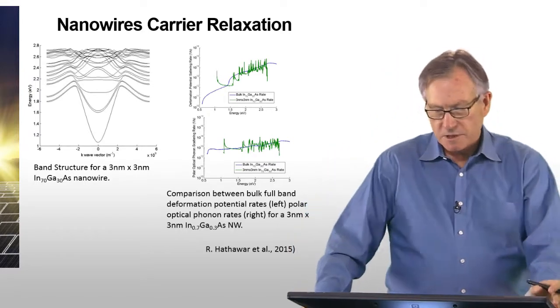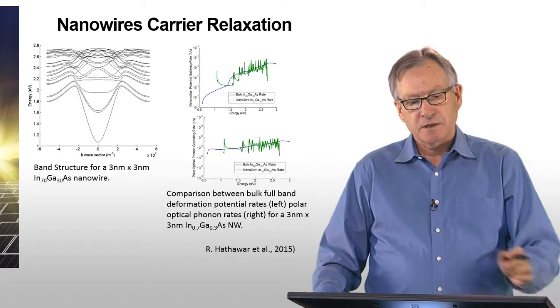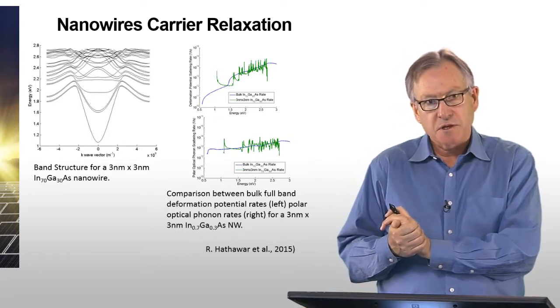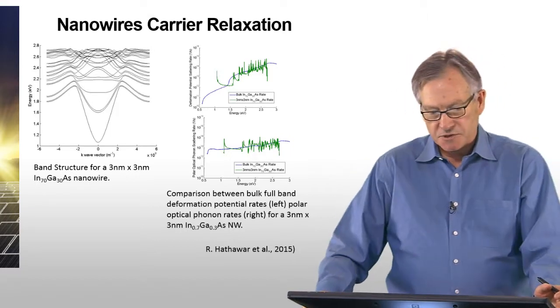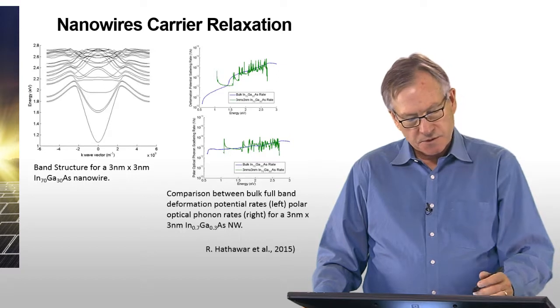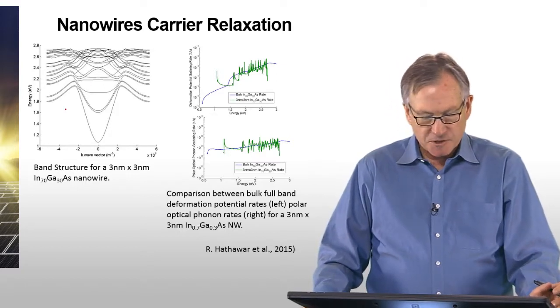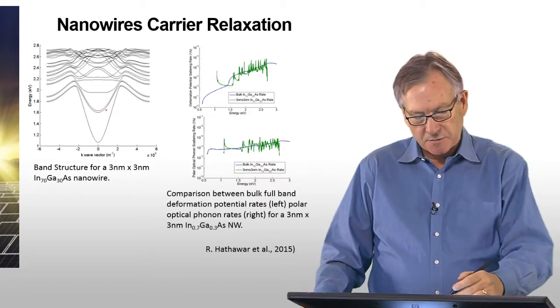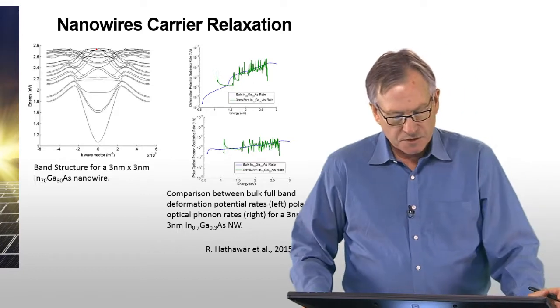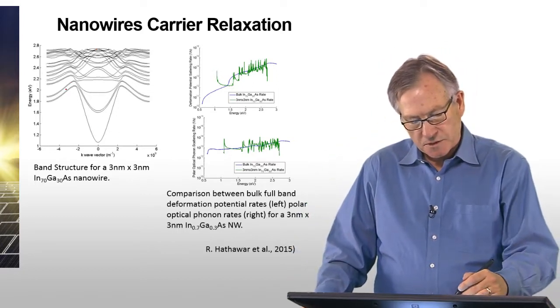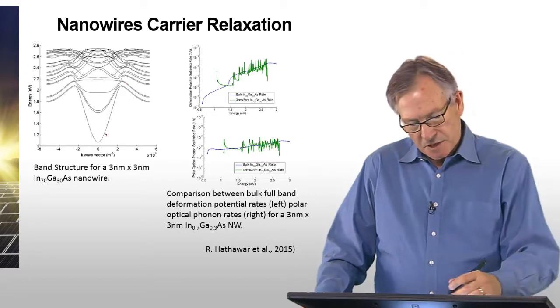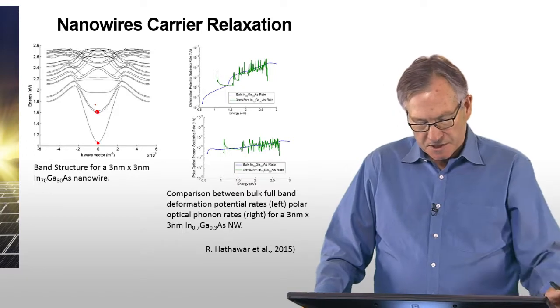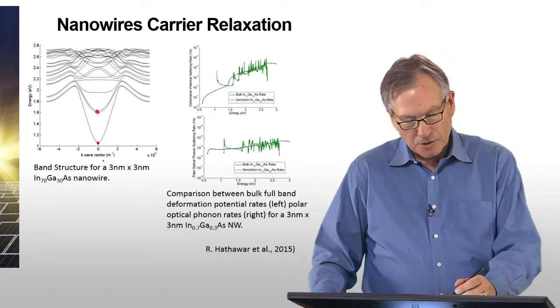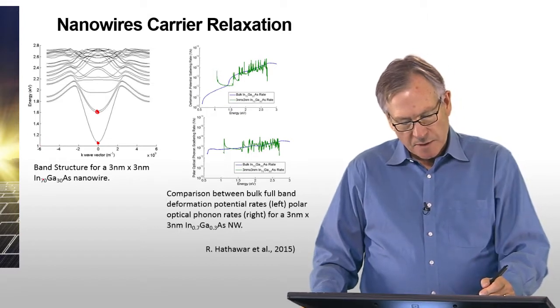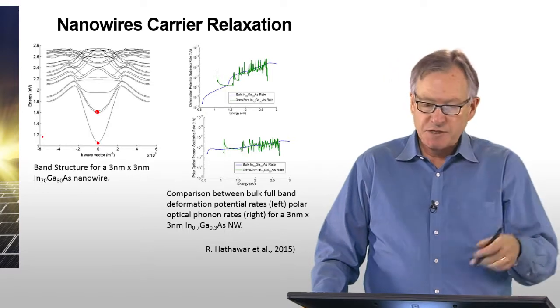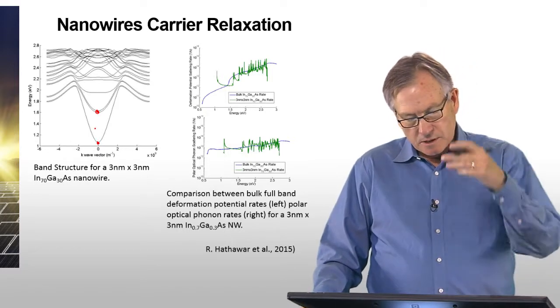This is modeling work that our group has been involved with, and it shows first the calculation, again using this tight binding representation, this sp3d5s* approach to the electronic states in a nanowire. So this is the conduction band states in an indium gallium arsenide nanowire. As you can see, the structure is quite complicated because you have many different levels, and because of the bulk band structure that's superimposed on it, there's a number of inflection points. This is the lowest confined state, and this is the next confined state, and the band gap of the indium gallium arsenide nanowire has been moved from the bulk band gap of about 0.5 eV all the way up to 1 eV. So just because of confinement, the band gap of this nanowire has been increased.